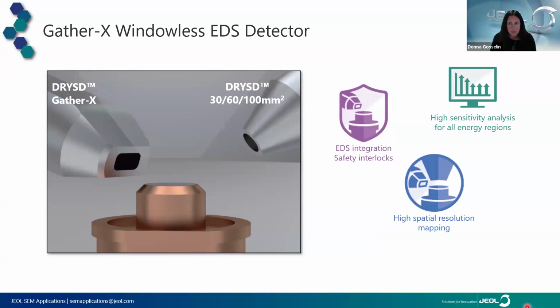The GatherX windowless X-ray detector, so windowless, so more efficient collection of the low energy X-rays, right down to lithium, is a great advantage. But it can perform analysis at any kV with very high sensitivity, and it's especially suited to the low voltage analysis for high spatial resolution microanalysis. It has kind of a racetrack design, which ensures very high collection efficiency of our X-rays, and also allows us to get up to very close working distance for very high magnification analysis. So we can really do X-ray collection as close as 1 millimeter.